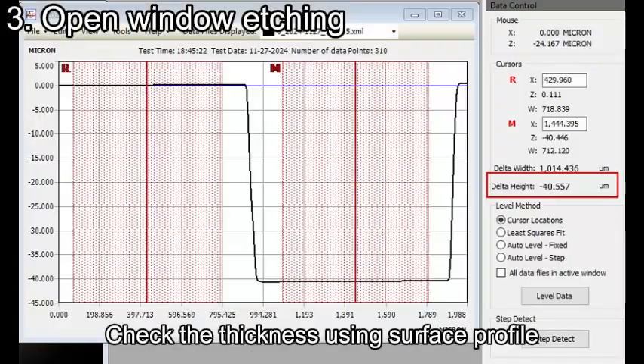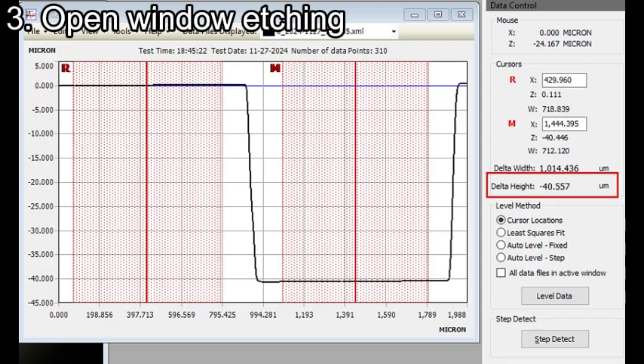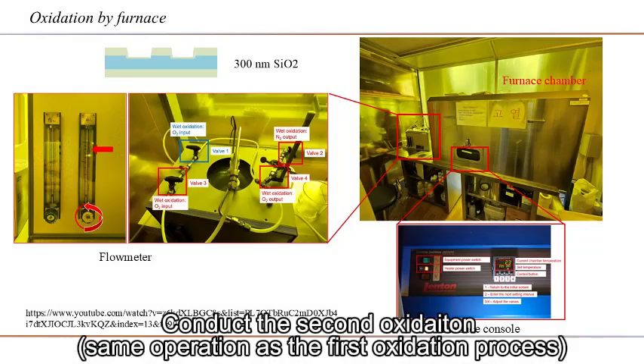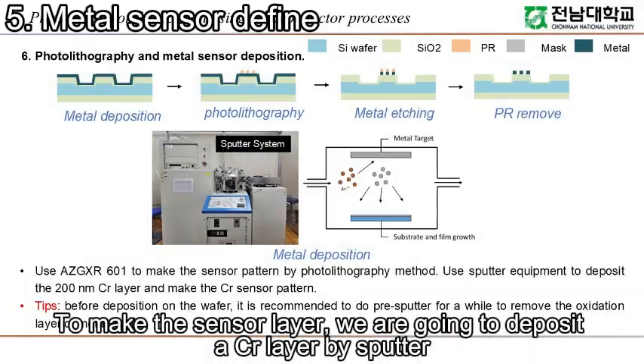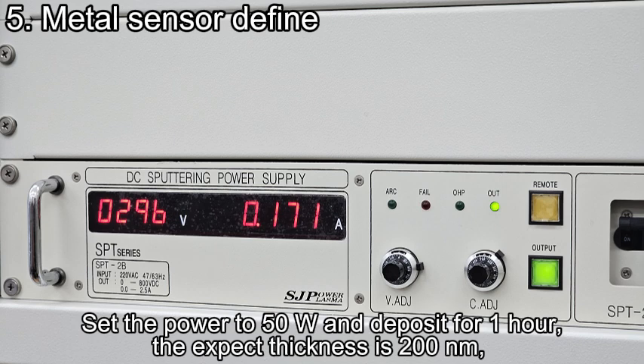Check the thickness using the surface profiler. Conduct the second oxidation, same operation as the first oxidation process. To make the sensor layer, we are going to deposit a Cr layer by sputtering. Set the power to 50 W and deposit for 1 hour. The expected thickness is 200 nanometers. Before starting deposition, a period of pre-sputtering is performed to remove the oxide layer of the metal.